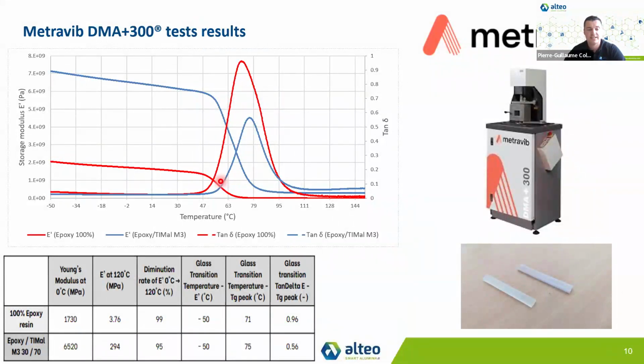But in any case, you can clearly see that it's not only a well-defined temperature where the thermomechanical properties drop down. It's really an area in between the range here of, for example, 50 to 90 degrees, I would say. So it could be also interesting for thermally conductive adhesive application where when you are looking for a battery replacement and adhesive dismantling, you can clearly see that you would better work at, let's say, 100 degrees, where the mechanical property of the adhesive itself are decreased.